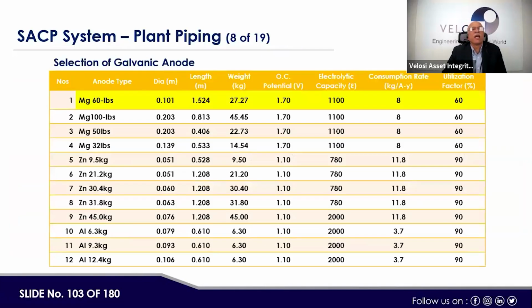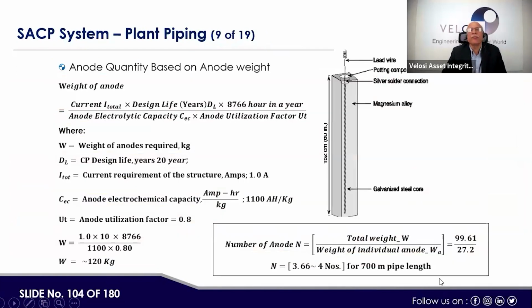Then here is selection of galvanic anode, for example weight wise: weight and size, diameter, length, weight, then OC potential, electrolyte capacity, consumption rate, and utilization factors come into the picture. Then anode quantity based on anode weight, like how many anodes would be required. First the weight, and the number of anodes comes to 3.6, so 4 numbers. In this way we can calculate the number of anodes required and the weight of each anode as well.